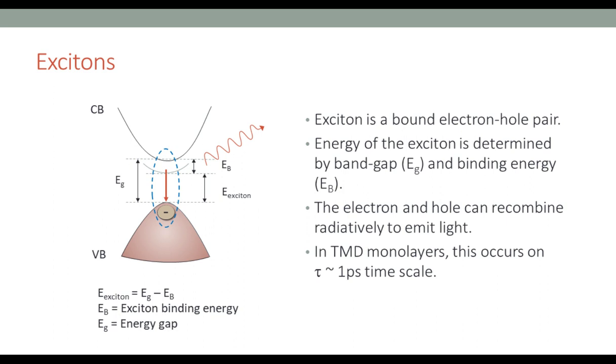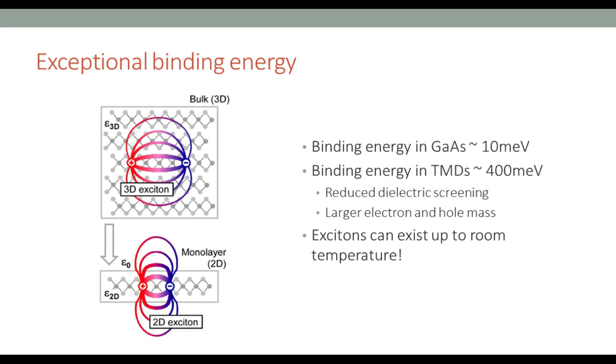And then the formation of this exciton, as I said, depends on whether you have a strong enough binding energy. So these materials turn out to have very strong binding energy. Gallium arsenide is a material that we often compare the TMDs to because it is similarly a high quality semiconducting material. But the binding energy in gallium arsenide is only around 10 meV, which means we're limited to very cryogenic temperatures to do any sort of exciton studies.